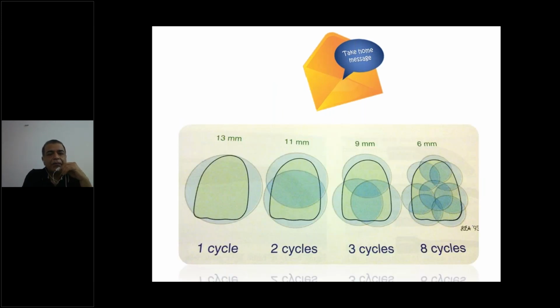Also, the number of cycles of curing on a particular tooth will depend on the size of your curing light. Many of us have a tendency to just put it on the tooth because the light is spread everywhere, and we give one cycle. Please note, if the size of the restoration is bigger than your curing light, you may need to give multiple cycles for it to cure.